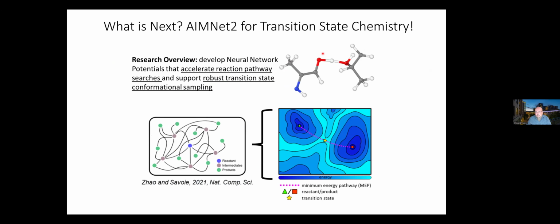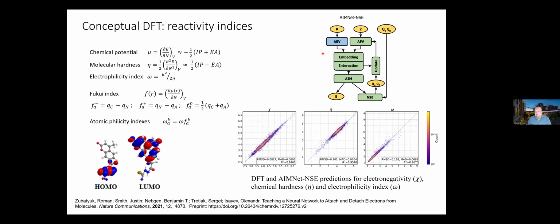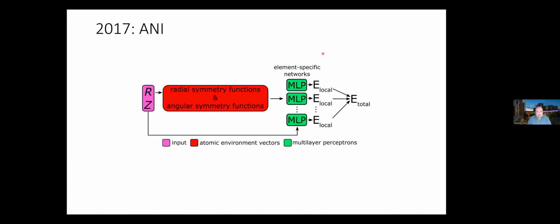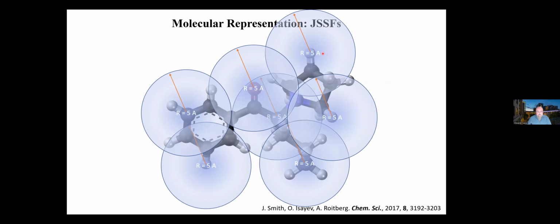The descriptor vector is actually consistent. There is nothing special here. We have periodic boundaries. You can work with the crystal cell. If I go to this slide, I think it will be best described. What essentially neural networks see is this constant size representation vector. Then depending on the size of the system, you'll have a different number of these things, but the framework handles that. Your descriptor size is always consistent. It's a fixed dimensionality of this atomic environment. For simplicity, you present them one by one, and it doesn't matter whether your system is 10 atoms or 10 million atoms. Your descriptor is always fixed. And if you have periodic boundary conditions, it correctly accounts for the symmetries, the central cell and all other cells. Yeah, thank you.